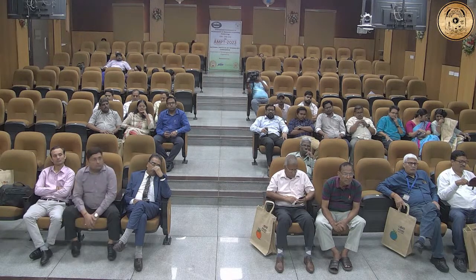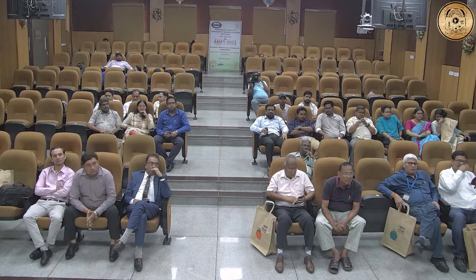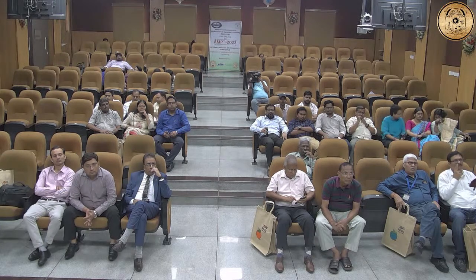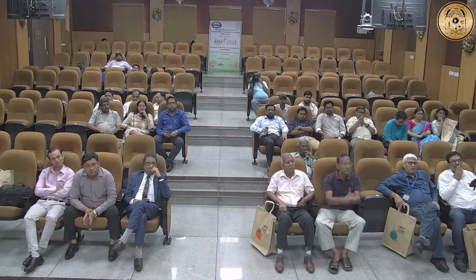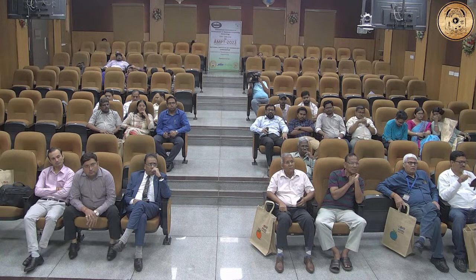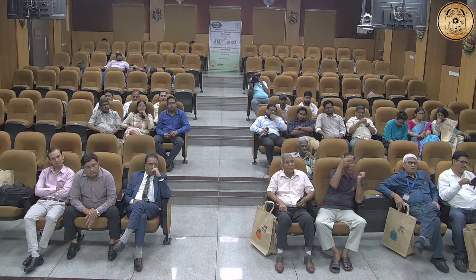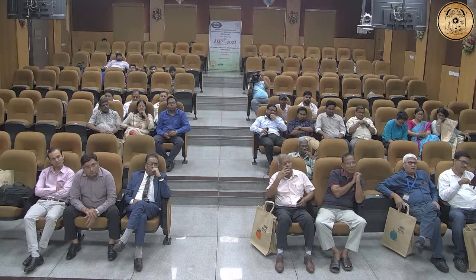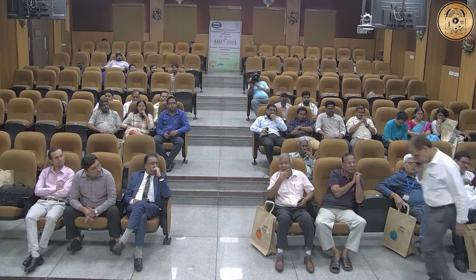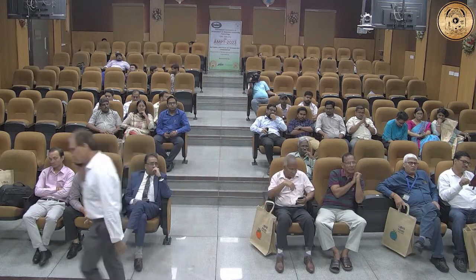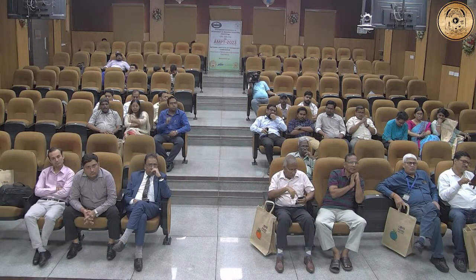अगर लास्ट स्टेज में हम लापरवाही कर देंगे, जितना भी अच्छा काम किया सब बर्बाद हो गया. And it is here that the game is played at the ppm level, 5 ppm, 10 ppm, 6 ppm. That is the level of oxygen we are talking about, and that is going to produce steel inclusions which may be just 20 milligrams in 10 tons of steel. Okay, very little amount, but if the inclusion is in the wrong place, in some sort of a curve or in some sort of a bend, then the load concentration will take place, and we will have failure or premature failure of the component.